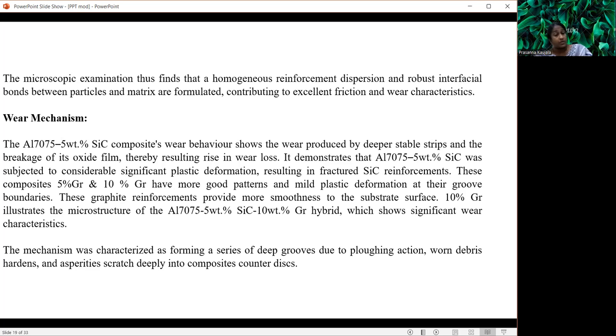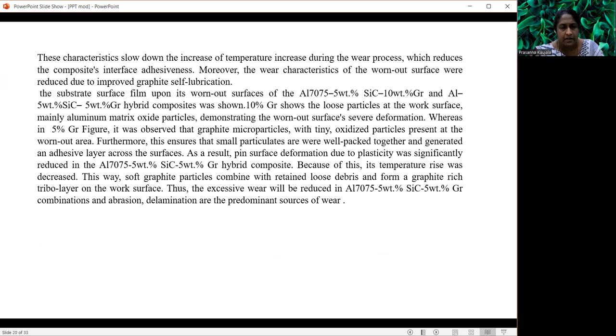Conversely, the hybrid composite's wear debris has mixed cores and fine particles with non-uniform patterns. So the mechanism is characterized by a series of deep grooves due to ploughing action, where worn debris hardens and asperities scratch deeply into the composite's counter discs. These characteristics slow down the temperature increase during the wear process, which reduces the composite's interface adhesiveness. So here are some of the worn-out characteristics found using the 5% and 10%